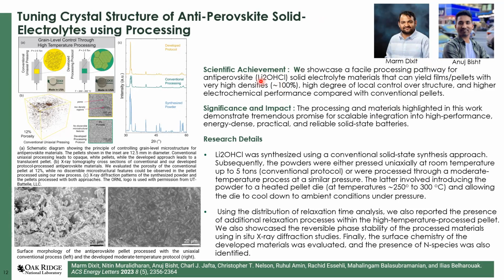This material normally is not in the cubic phase at room temperature, but by coming up with a new protocol, he was able to stabilize this material in a phase that would have very good properties as a solid electrolyte. So this is important because being able to manufacture materials and process them in such a way that they can be used in real devices requires fundamental understanding of the process.